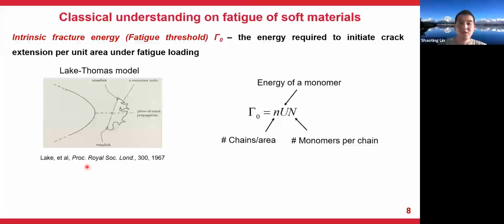So my interest is to understand the fatigue of soft materials at the network level through combined experimental and theoretical efforts. One classical understanding on fatigue of soft materials dates back to the Lake-Thomas model, which defines the intrinsic fracture energy, or alternatively fatigue threshold, as one physical quantity to characterize the energy required to initiate crack extension per unit area under fatigue loading. So physically, the value of this energy is equal to the energy required to fracture a single polymer chain times the number of chains per unit area of the crack surface. The model has been very successful and widely used even nowadays, in the sense that it can be generally applicable to different kinds of polymers, hydrogels, and elastomers.